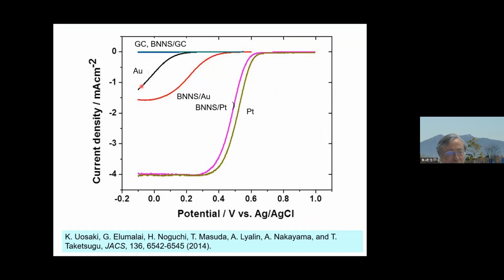So this is the summary. In the glassy carbon case, even with boron nitride modification, nothing. In the case of gold with boron nitride, it becomes like that. In the case of platinum, platinum itself is quite good, and the surface modification with boron nitride became a little worse actually. Compared with platinum, it's very bad, but still there's a possibility of improvement, or boron nitride is acting as an electrocatalyst.